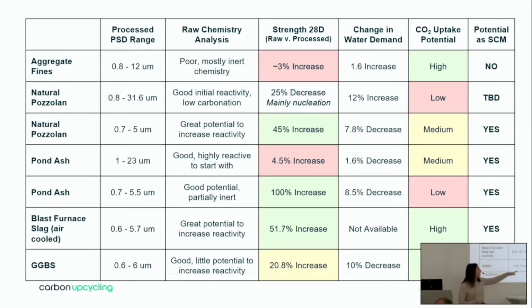And so at that very last column, we made the determination that 5 of our 7 materials were good candidates to consider future testing with, to do some more analysis on the chemistry and on the strength performance. And we determined that one of them was probably not a good candidate, and then one is to be determined. We had a bit of interesting results, so we're going to pursue that one further to figure out if we would recommend it as a candidate.